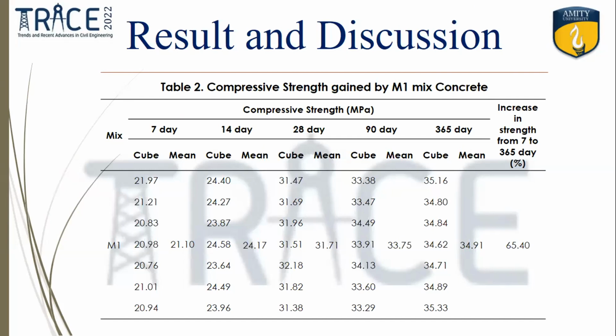As you can see, for the conventional concrete, as I said, I chose the M30 mix. So on the 28th day, my strength was 31.5, and over here, my strength was 31.71. As the days increased, on the 90th day it became 33, and on the 365th day it became almost 35. But as you can see, the increase in strength from the 7th day, that is from 21.10 MPa to 34.91 MPa, was almost 65%.